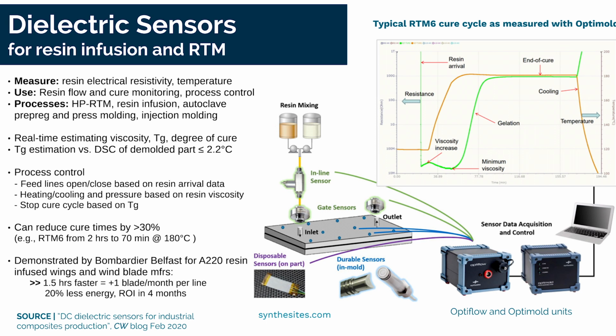So for dielectric sensors, what it's actually measuring is the electrical resistivity in the resin. So it's actually part of the material state, right? And you can see in this graph, you have resistivity here, and then you have the temperature here versus time. And what you can see is we actually get to see a lot. We can see when the resin's arriving. We can see the viscosity changes. We can see as the resin gels and reaches its glass transition temperature, its Tg, that we're reaching the end of cure. And so all of this is incredible. We have a lot of visibility into what's going on.